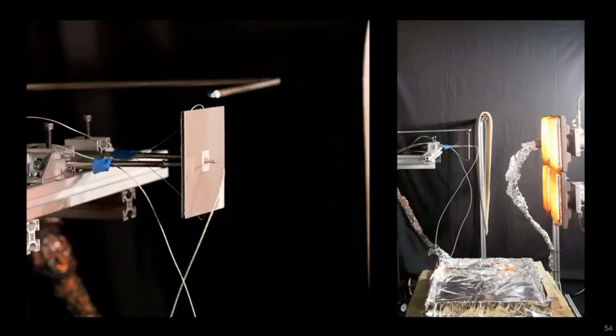Flaming will then become well established over the front surface of the exposed polyethylene core that remains on the sample, and burning droplets of polyethylene core material will begin to fall from the base of the specimen and land in the debris tray. The rate of burning droplet production will increase until there's a near continuous stream of burning polyethylene core material falling into the debris tray. And after about 2 minutes, the dripping will cease, as all the polyethylene will be gone, and burning will continue only in the debris tray as a pool fire. Eventually, all flaming will cease, and the experiment will be halted. So I'll now let it play, and it should pause periodically so that I can point some things out.